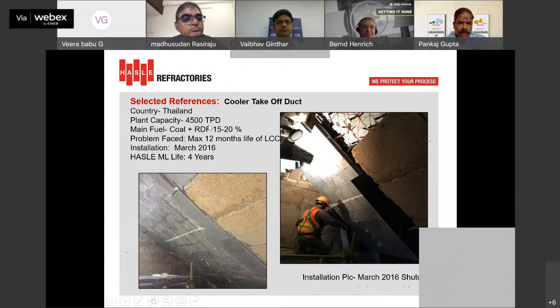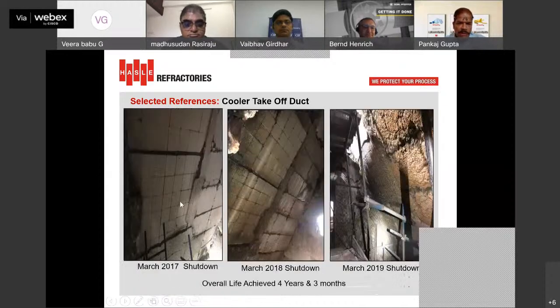So this is a plant using 15 to 20% RDF, and they are getting a life of 12 months only in their takeoff duct area. After installation of modular lining, they were able to achieve 4 years of life. This is the picture after 1 year. This picture is after 2 years and after 3 years, and completely they have got a life of around 4 years in this plant.